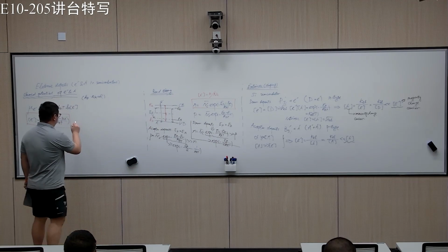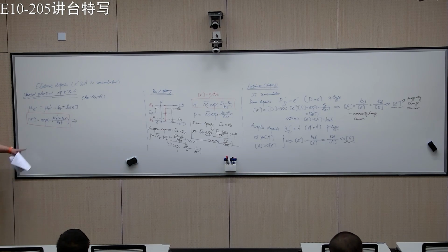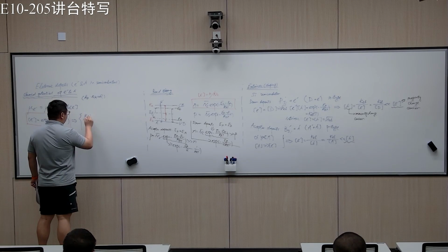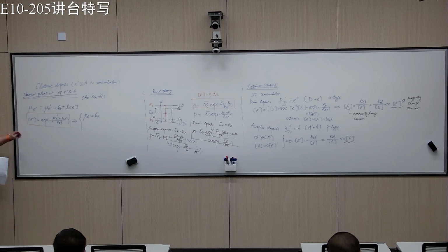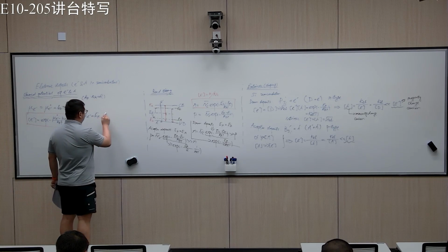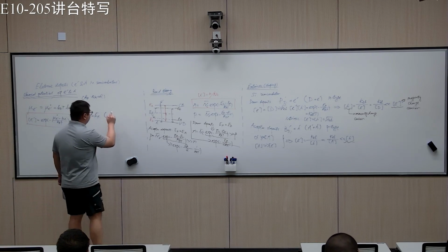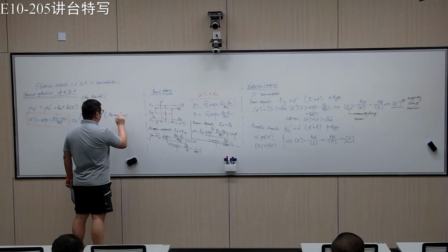So what you end up with is you will immediately know what these two values are. So this is basically the Fermi level. Which means that the chemical potential of electrons is the Fermi level. In solid state physics, it's often directly written in the textbook, which means the concept of the Fermi level is basically the same as the chemical potential.